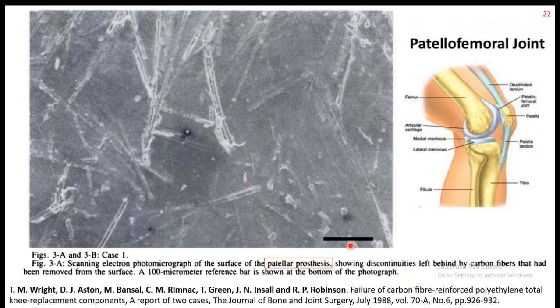This is another issue, and in fact UHMWPE and carbon fiber composite has been tried clinically. This is a paper where failure of carbon fiber reinforced polyethylene was studied - in some patients it did fail, and those failed specimens were looked at. They found that these fibers, on the surface where sliding takes place, actually get pulled out, because these fibers are in a horizontal condition on the surface and get easily pulled out because of the shear stress. This is one big issue, and because of this, this composite was tried quite early on in 1988, but since then has not been tried so much.